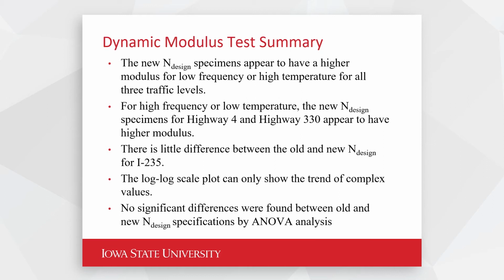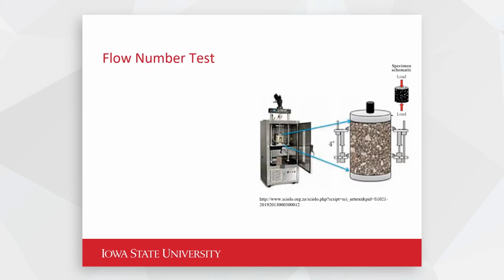They were statistically essentially the same for I-35 or I-235. And you would think that would probably be true since we only changed the binder content by about 0.1%. Okay. So we can go to the flow number test.